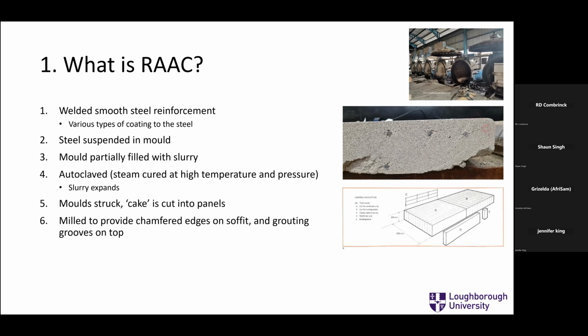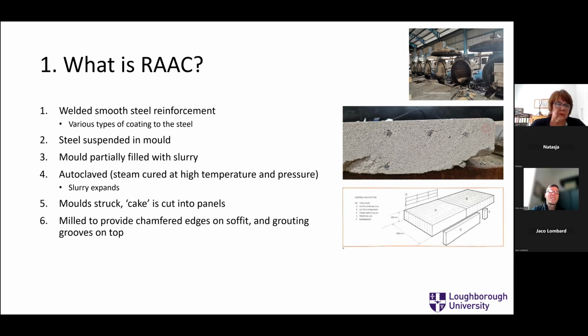And we make it not in individual elements, and they typically come about 600 millimeters wide and about 200 millimeters thick as a typical cross section. So we don't make them in molds like that. We make them in very big slabs, like the photo there, called cake. They call it a cake. So they bake a big cake, which is really efficient for productivity. And then they cut it up. So they literally use a big cutter, often a wire cutter, like a cheese wire cutter, but on a big scale. And they slice up the big section into smaller panels. And then they might mill the edges, cut it to shape slightly, put some chamfers on, shape it slightly.